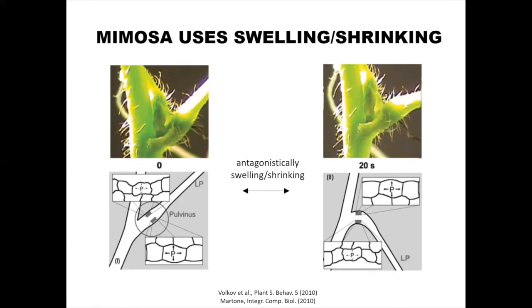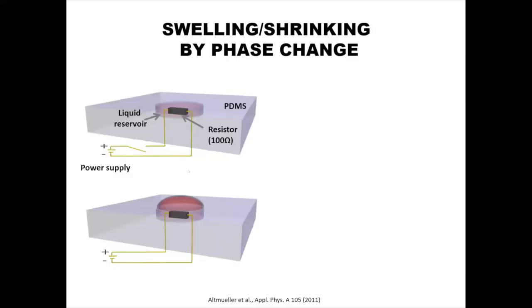And we took this as an example to make a little phase change actuator, and today we actually saw some materials that use this phase change, in the very first talk, or the second talk and the first talk. What we did is, I've heard already that people use a lot of silicone, and this is where I come from, the background of stretchable electronics. So we use silicone rubber, and what we created was a little liquid reservoir within our bulk silicone material. We inserted a resistor and connected it up to a power supply. And on the top, we put a very thin membrane to seal this liquid in.